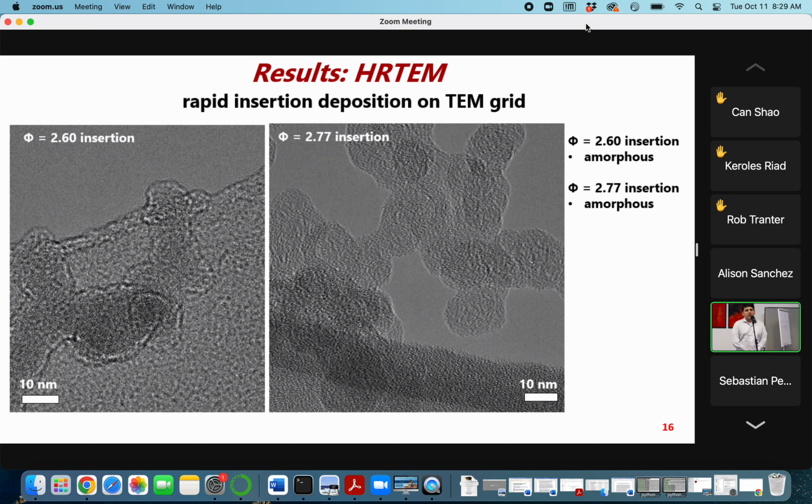I think that there are temperature effects in the flame and outside of the flame during deposition that can be important. One thing that can be important in the flame would be if you have a lot of precursors and then it undergoes a certain cooling rate at this deposition surface, that can induce some crystallization due to the cooling of low vapor pressure materials and things like that. And then outside of the flame as well, depending on the deposition temperature, you can have this multi-component gas flow coming into the deposition surface. There's a lot that we're looking into right now to try to isolate these competing processes.